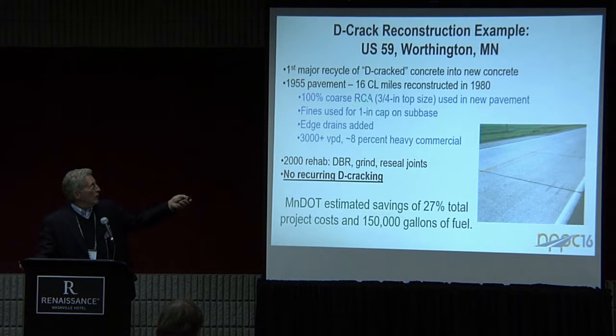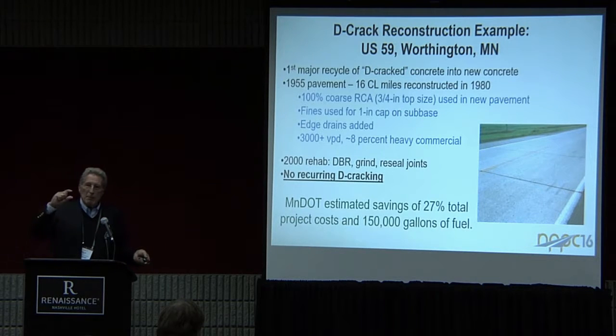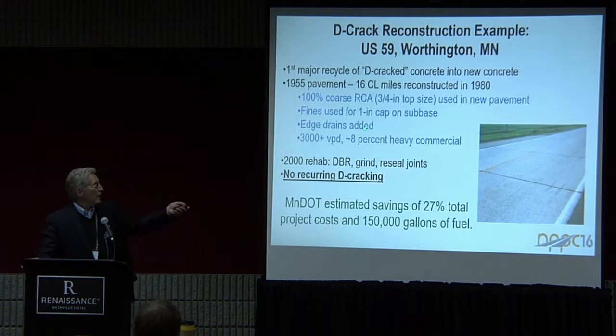Used all the coarse aggregate, 3/4 inch top size in the new pavement, took the fines and put a 1-inch cap on the existing subbase, and of course that's going to solidify up then with a little bit of moisture and give you some additional support.